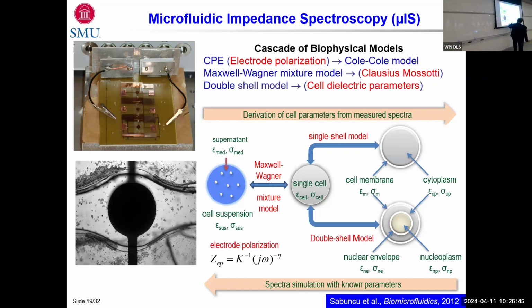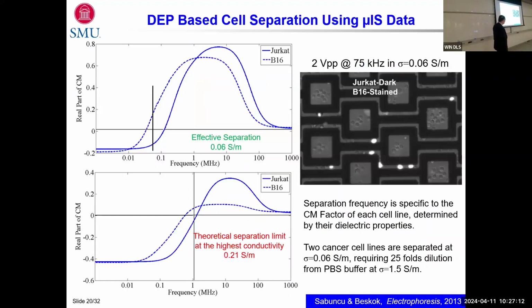If you know this, then you can draw cell parameters from measured spectra, and if you know the cell parameters, you can simulate what you will be measuring if you did this experimentally. So it can go both ways. And the problem is, of course, it's a nonlinear least squares fit algorithm that we use to fit all those parameters. And we can be challenged whether the solution is unique or not. But we have identified methodologies to do that right. So looking into that, we were able to create this same design that we have seen earlier.